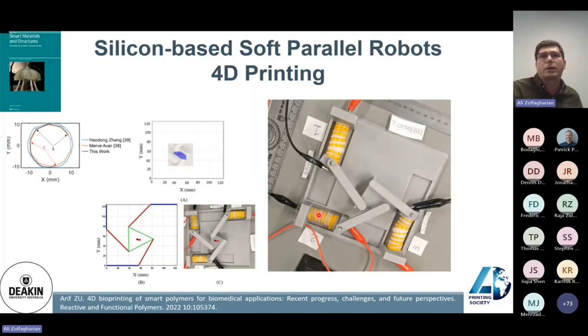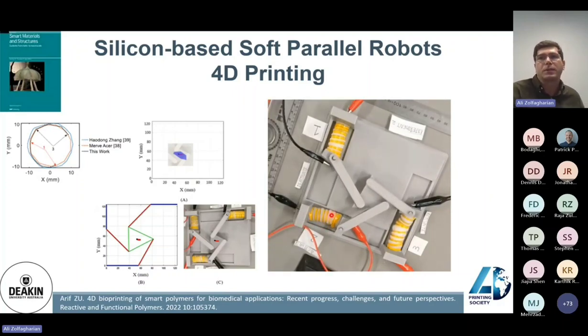Nickel chrome wires are inside of these silicon-based soft actuators, and when applying electricity, they heat up and expand because of the ethanol that is entrapped in the silicon. It leads to some actuation.